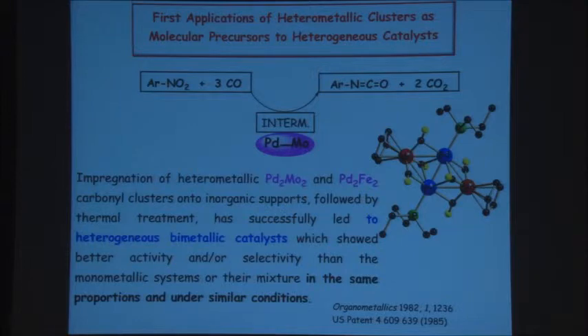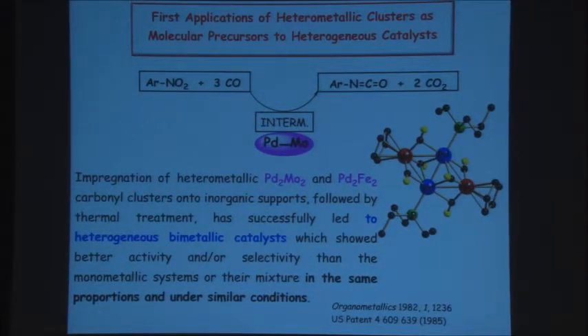The first candidate, and that's back in the early 80s, and this is, I think, the very first example of a molecular cluster used as a precursor to nanoparticles. At that time, to put things in perspective, we were very pleased and proud in my group to make compounds that we thought were aesthetically very pleasing. Here is a palladium-2 molybdenum-2 cluster, a planar structure, a center of symmetry, phosphine ligands here, cyclopentadienyl and carbonyl ligands around the metal centers. So that structure was very unique. This was the first palladium mixed metal cluster ever reported, so we're very pleased with that.